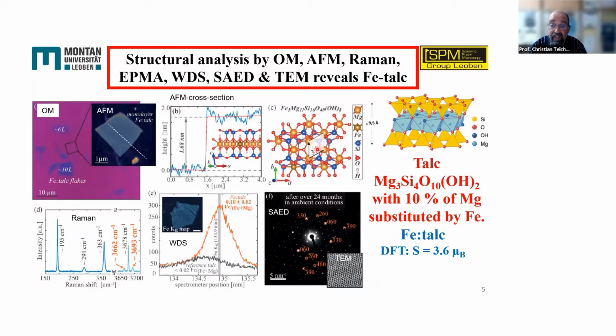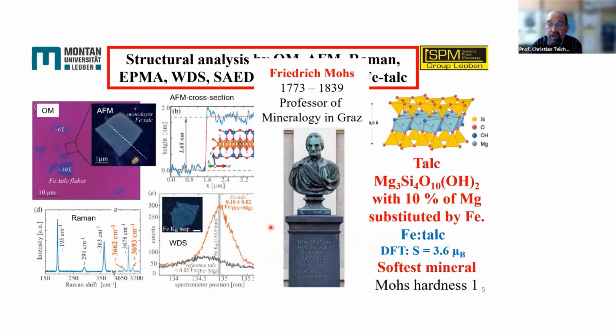And now there is about 10% of magnesium replaced by iron. So from the hematite-rich region, iron interdiffuses. And so we have here really an iron-rich talc, and DFT calculations show that the spin state is quite robust with 3.6 μ. And just to let you know, talc is the softest mineral that we know, that is Mohs hardness 1, and in fact Friedrich Mohs was a professor at Graz University of Technology, just 50 kilometers from here.